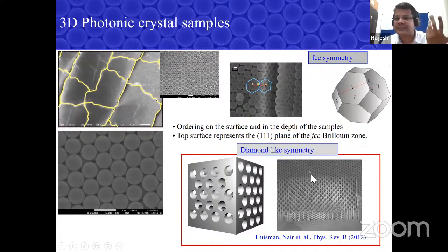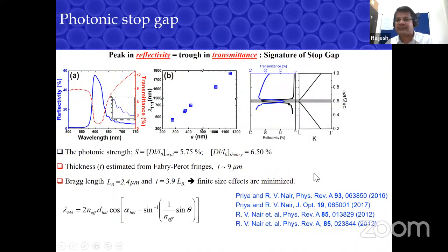Okay. So once you make a sample, how do you characterize it in the lab? As I said, we need to see whether it has a band gap or not. So we do an experiment. We measure the reflectivity as a function of lambda, and simultaneously we measure transmission. The reflection shows a high reflectivity around 600 nanometer. And if you look at transmission, which is the red dotted curve here, the transmission also drops and becomes close to zero, then rises up and goes to a high value. So if you launch light at 600 nanometer, it cannot propagate because close to 60% of light is reflected back.